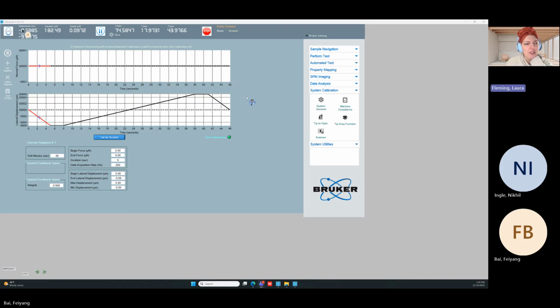So here, right, we've looked at this before: displacement, actuation, and sample. This is the sample force we've been using to determine if we were in contact or not during imaging. Now, there is an X parameter here. You can see it's moved to that imaging position of negative 9.9 as expected. It also updated your mode to scratch mode. So we turn on the scratch axes and it immediately moved to the imaging position. It's a good sign. It means it's actuating well, it's moving well. So that's what we're looking for.